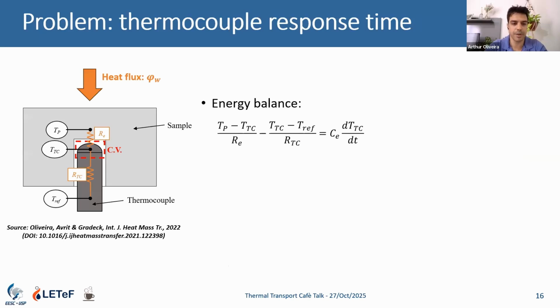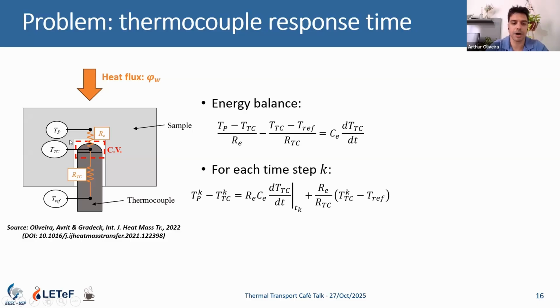A few years ago, we made a very simple model to correct the thermocouple signal, where we consider an energy balance on the thermocouple tip. We can model the thermocouple response very easily, considering response time given by the thermocouple capacitance and the contact resistance with the part, plus a heat loss parameter to consider as well.